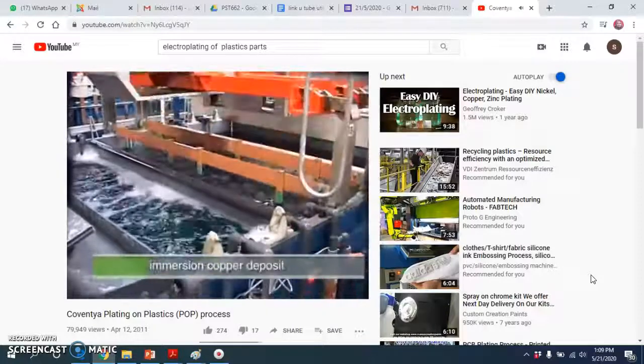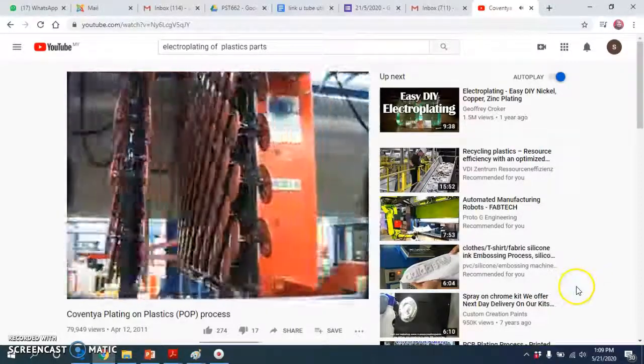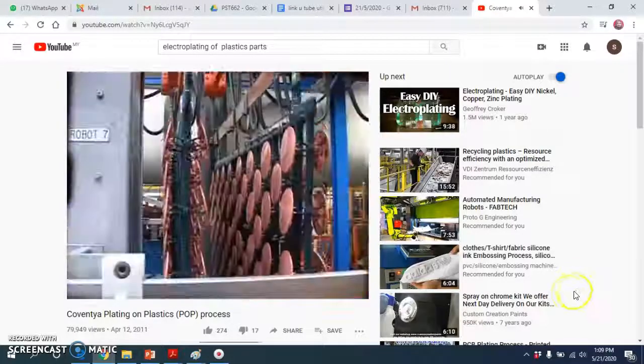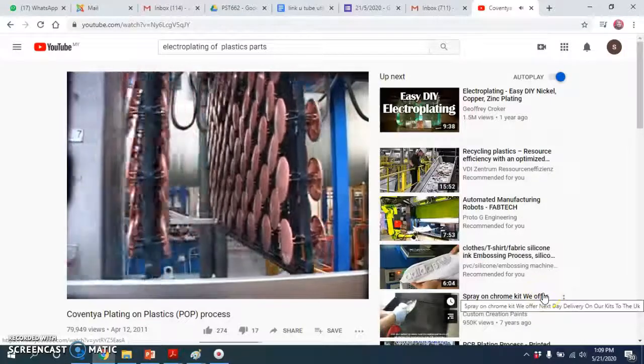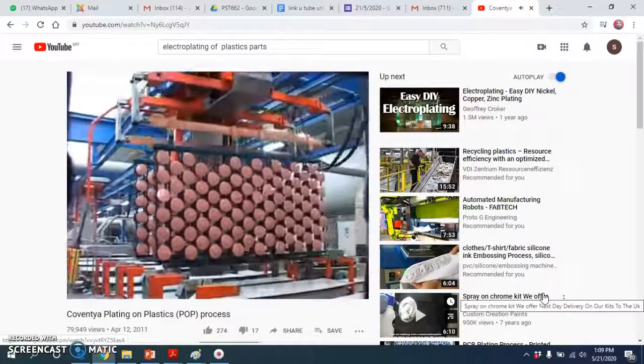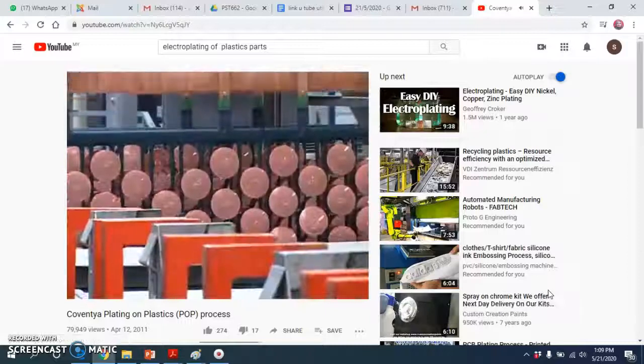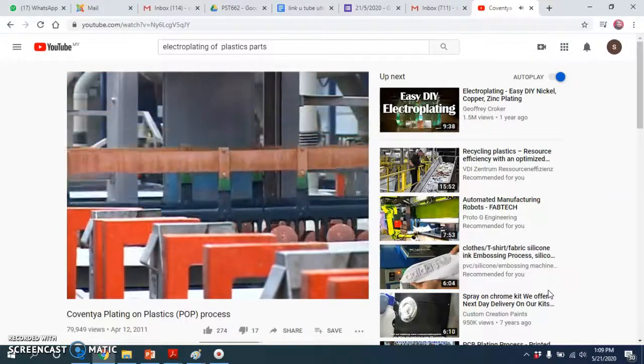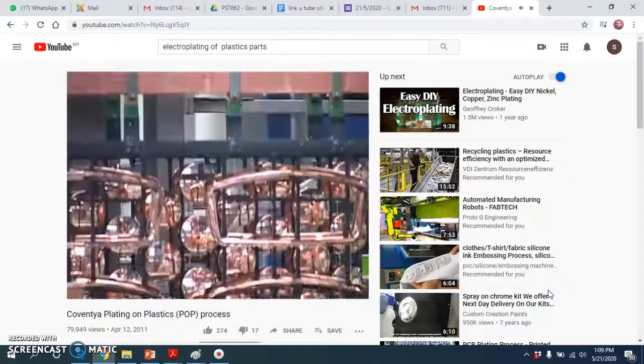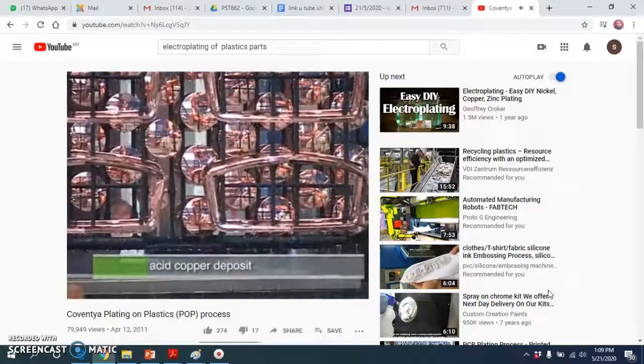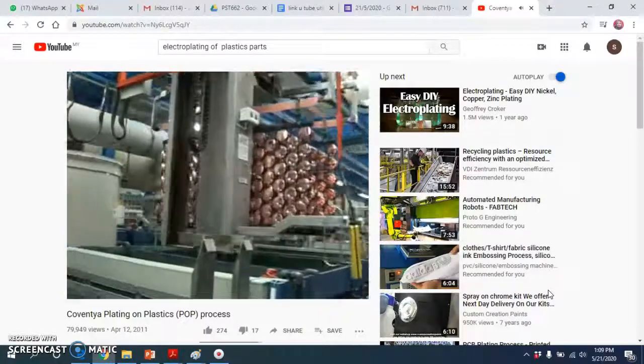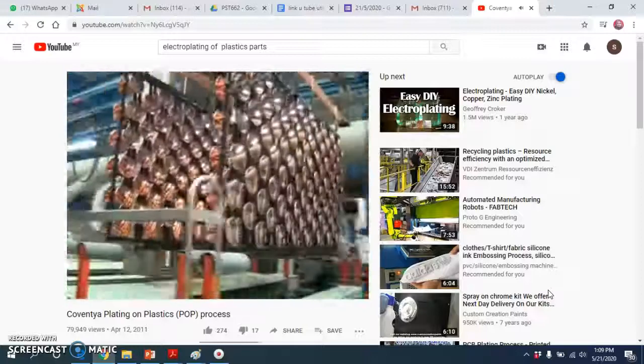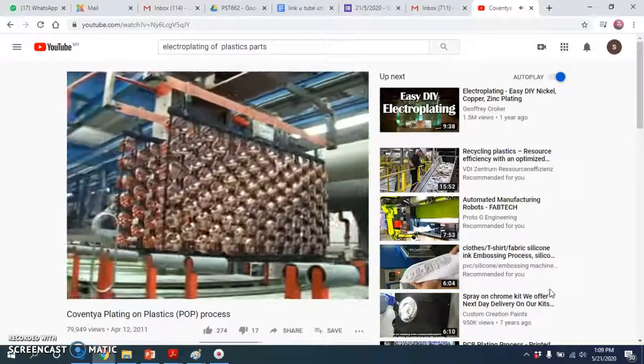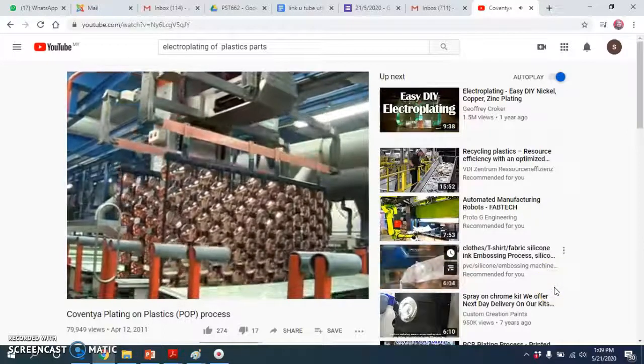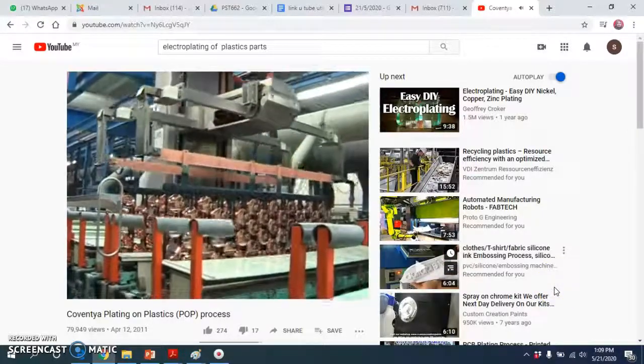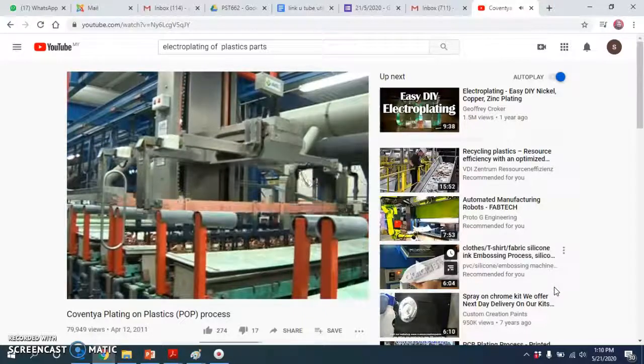After creating the initial conductive electroless nickel, racks of parts are processed through an immersion copper or nickel solution to further improve their conductivity. Next, a 20 micron thickness layer of copper deposited from an acid copper electrolyte provides a metal layer on the etched plastic surface, while also producing a bright smooth deposit. This layer also provides adhesion between the plastic and other plating layers, which is important. It also prevents formation of cracks in the surface of the parts. A bright deposit allows